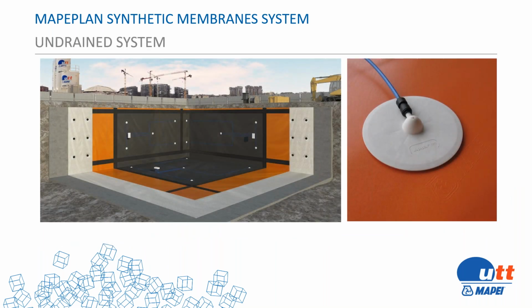In the PVC membrane system, we use the water stop as a combined part of the system. For all construction joints and all expansion joints, we have a water stop to seal the joint. And we weld this water stop to the membrane to create what we call a compartment. One compartment is around 1500 square foot of area. Every compartment will have the testing and injection flange. We use the test and injection flange for testing the waterproofing system after putting in the concrete, and also in case we have any damage or leakage, we can repair the system.